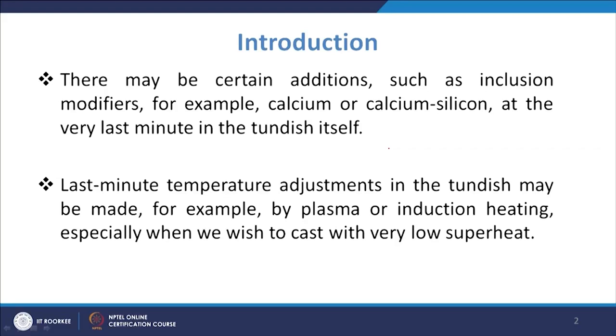In areas where temperature drops significantly, a heating mechanism is needed to keep the liquid above its melting point so that undesirable solidification does not occur inside the tundish. We use plasma or induction heating especially when casting with very low superheat, where an undesirable temperature drop in certain regions could produce undesirable outcomes.